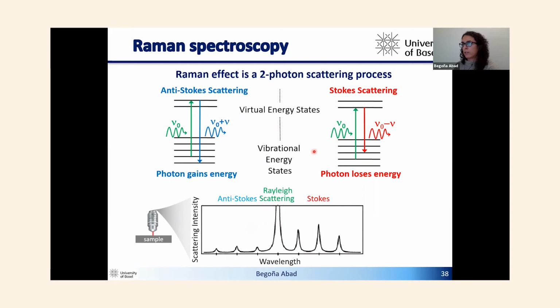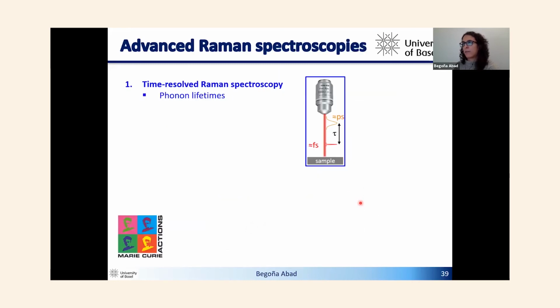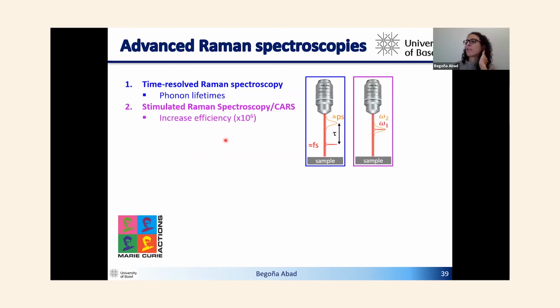So in the group, we are doing a lot of Raman spectroscopy, but in my case, I'm focusing on advanced Raman spectroscopy. And when I say advanced, I mostly mean pump-probe Raman spectroscopy, where we are going to do time-resolved spontaneous Raman spectroscopy, where we will be looking at phonon lifetimes. In this case, we will use a pump with a femtosecond pulse duration, and we will use a probe with a picosecond pulse duration to be able to extract the phonon lifetimes. However, that is sometimes complicated, it requires a lot of time, and the signal is weak.